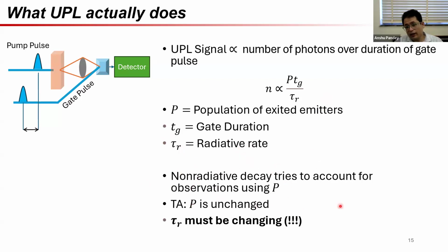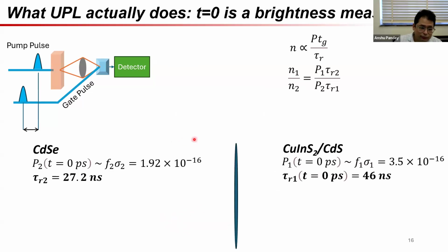And now that we are actually seeing all this, it creates some interesting things for us, because this seems to suggest, because P is not really changing, that's courtesy of the quantum yield, that's courtesy of what TA is saying, P is not changing at all. This means that the radiative rate itself must be changing. Certainly, we are not changing the gate duration. So this establishes nothing else but that the spontaneous emission rate itself must be changing, which is a gigantic surprise to anyone who knows what we are talking about over here, because we also were very surprised seeing this.